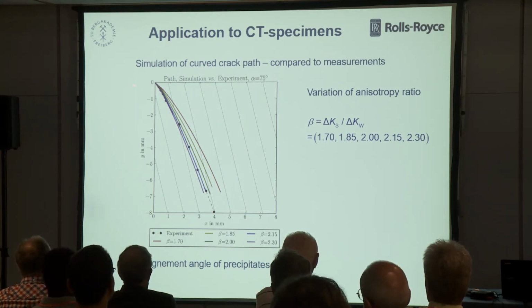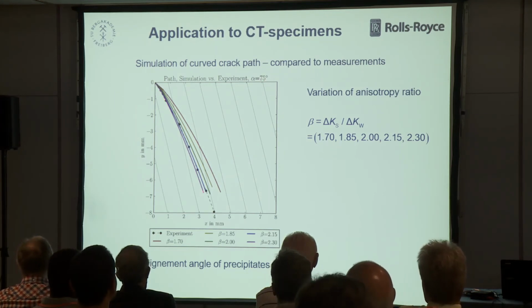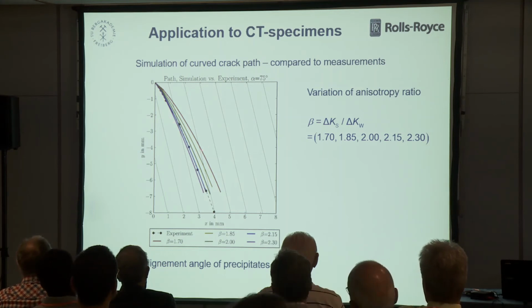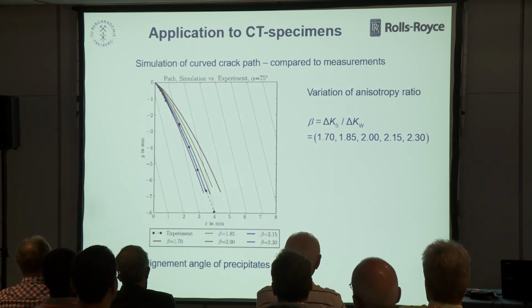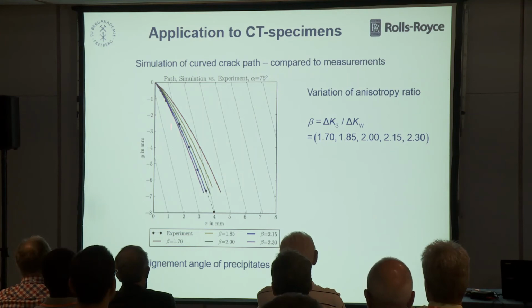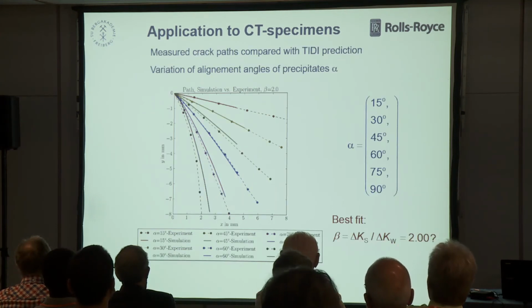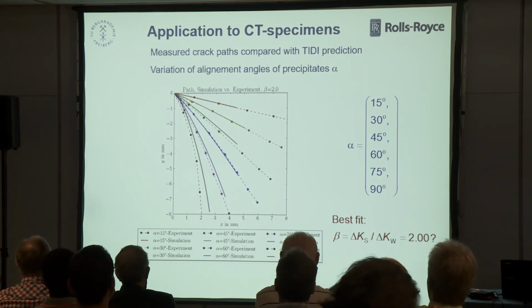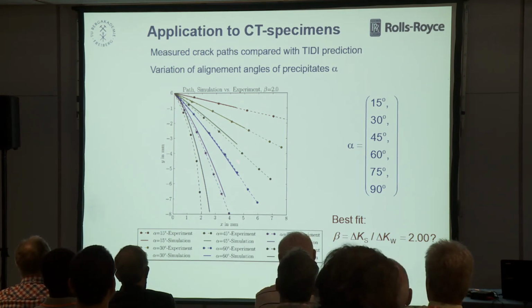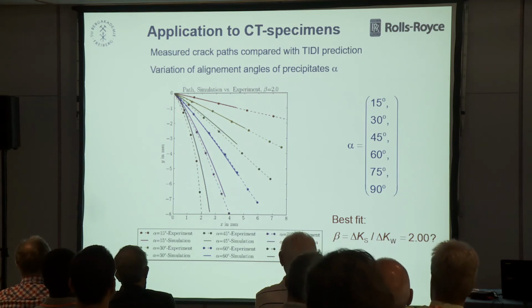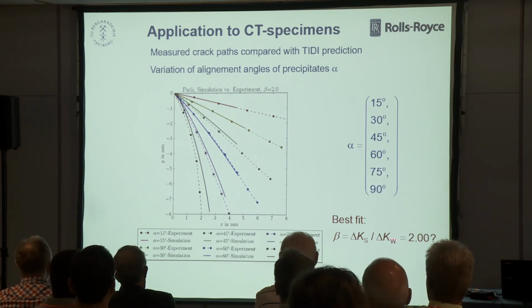And what you see here is for alpha 75 degrees. The experimental points are the dots, and the other lines are for the different beta values. So it depends, of course, on the beta. The higher the beta, the stronger is the deflection. And now we did it for all angles and found that for the experimental dots and our simulations, the crack path agreed best with a fit of beta equal to 2.